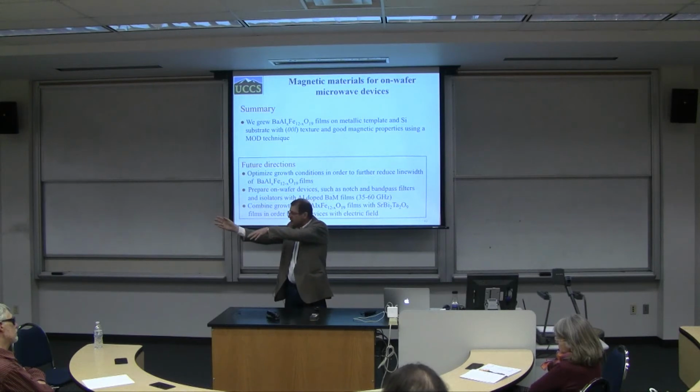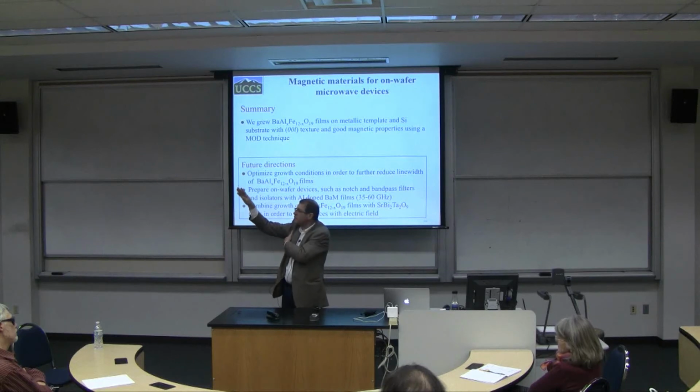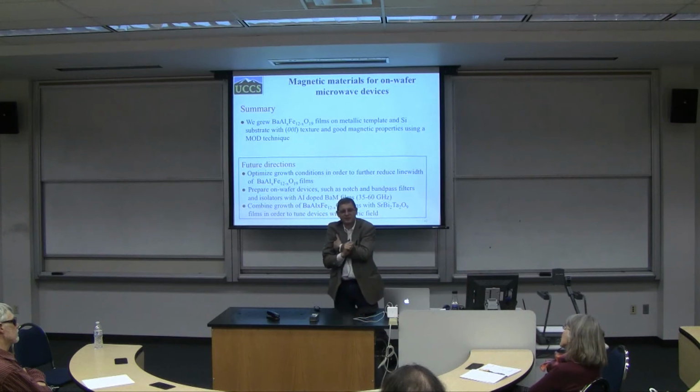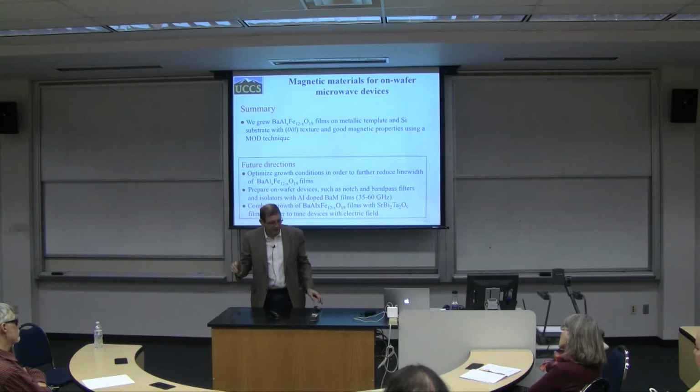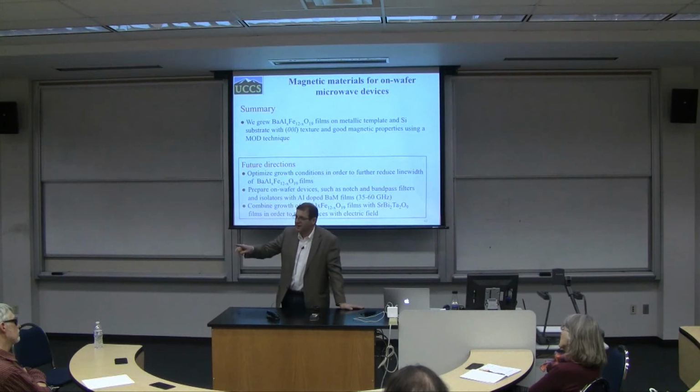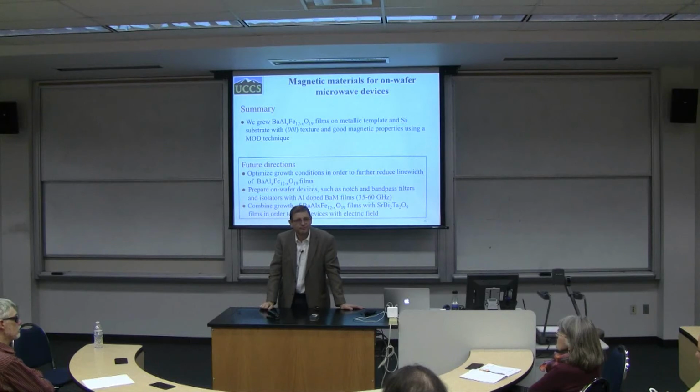A thermal vibration, a phonon, hits this thing, and what it does is precess to the equilibrium position. For metal, it typically takes one round of precession, because damping is so large. For other materials, like yttrium iron garnets, this precession can last microseconds. So it's an incredible difference.